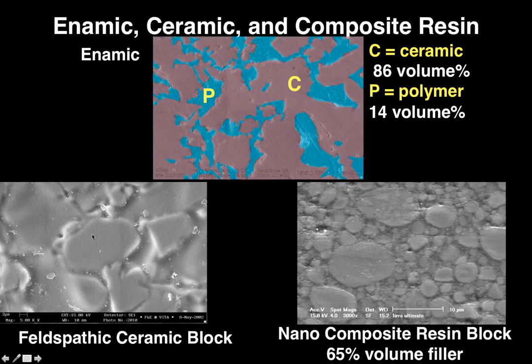So again, if you look at a feldspathic porcelain, individual particles, this happens to be the Lava Ultimate, which is supposed to be a nano composite material or a nano ceramic. This is a 10 micron scale bar, so some of the pieces in there aren't exactly nano, but there are some nano pieces here. Usually nanoparticles don't want to stay nano. They tend to clump together. It's very difficult to make a truly nano particle material. But you can see the particles are all individual, and they're all surrounded by a polymer.